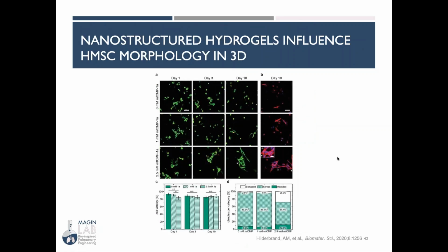And you can see inside these networks that the cells are alive and thriving, and there is actually a dose-dependent response of cell morphology and spreading to the collagen peptides that are inside the material. So you see here, the larger dose of collagen peptides induces more spreading and elongation of the cells versus no collagen peptide inside the material. So I think this is an exciting way to start studying some of the things that are going on in a collagen-rich microenvironment, such as a lung that has experienced pulmonary fibrosis.